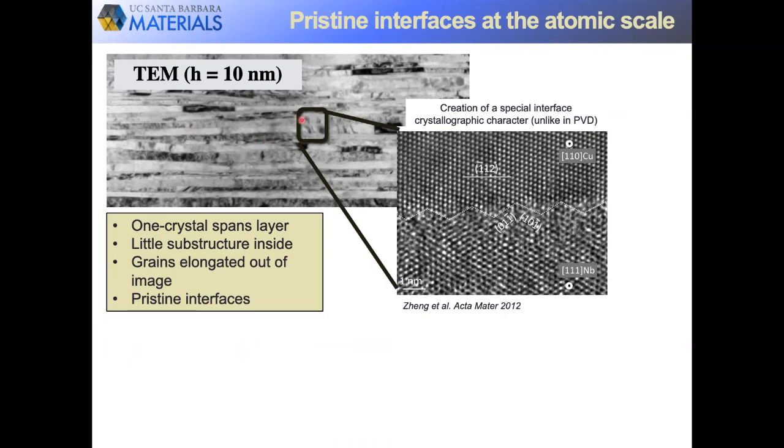And to our surprise, we found that these interfaces are rather regular and periodic, which we would not have expected because of all the interactions with dislocations that would have been involved. So this type of high resolution TEM imaging was done in several parts of the material, and every time we found that they had this regular topology, and they were actually also rather sharp.